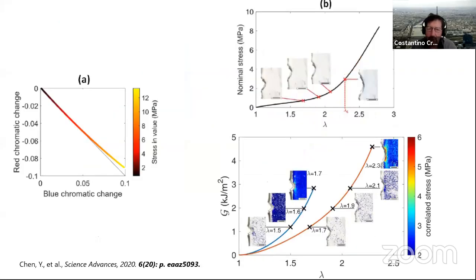Now, it's possible to calibrate that. So if we look at the red and the blue, we can make one of these maps here on the left, and we can associate to each combination of red and blue change relative to a neutral color a value of stress. So this can be done in uniaxial extension.